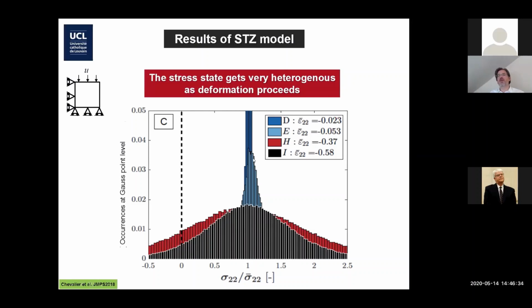At 5%, you get some distribution, meaning that in some regions you get transformation, in other regions you don't, and there is a pattern of stress. But look at 30% or 60%. The distribution of stress is enormous. Up to a point where some elements at gauge point level show stress which is opposite to the applied stress, meaning you're under compression, but there are regions of the material undergoing tension. So the distribution of internal stress is huge. And this is related to this heterogeneous process of transformation.